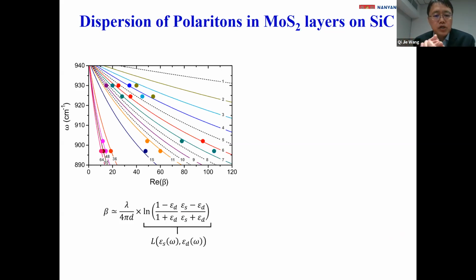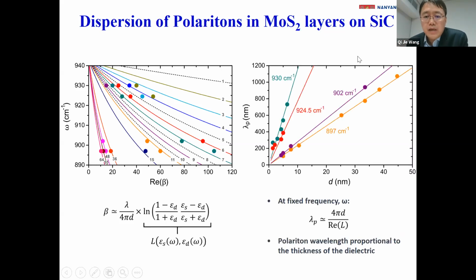Good agreement has been achieved, and then we fix the excitation frequency, and then we plot the Phonon-Polariton wavelengths as a function of the thickness of the dielectric layer on the top. Now we see a very nice linear fitting. So this should fit into this linear relation. L is related to the permittivity of the system.